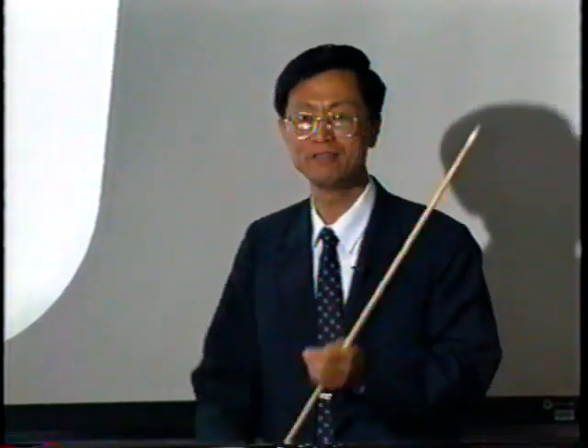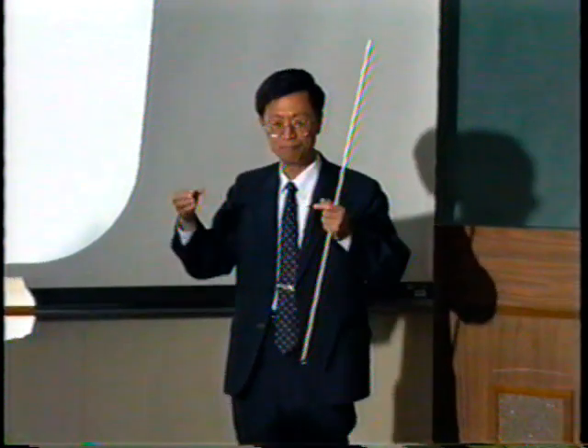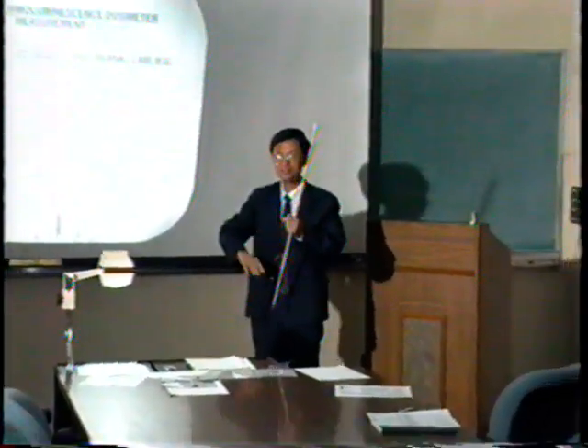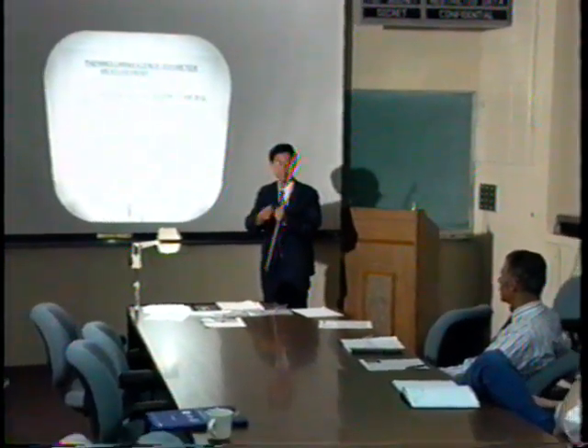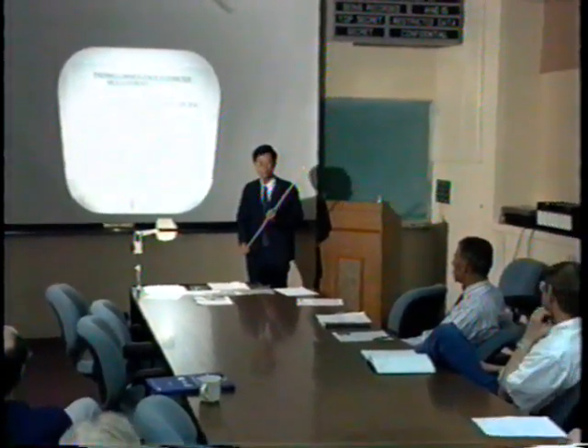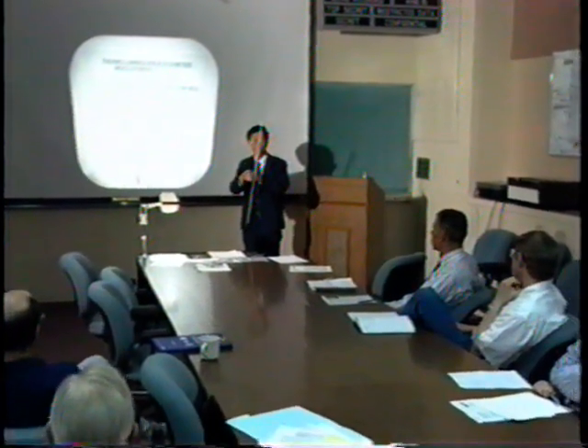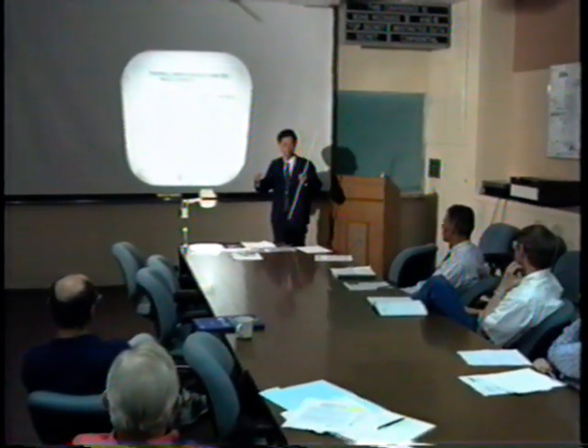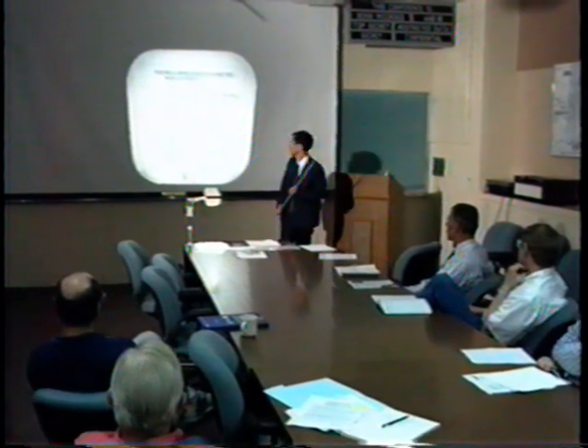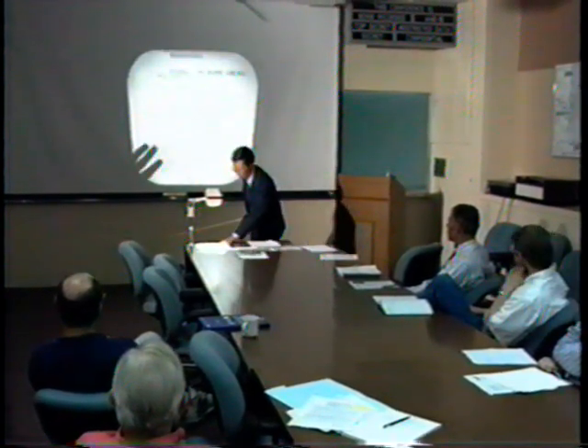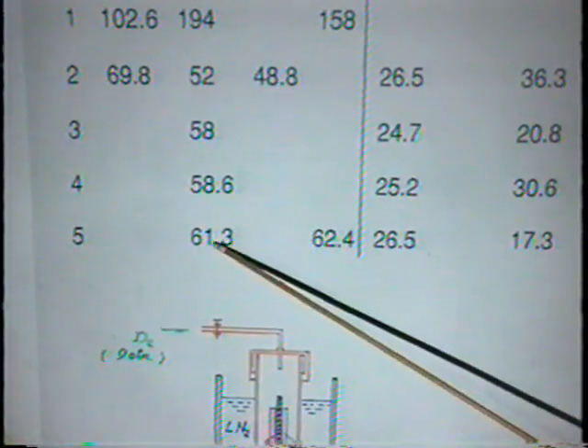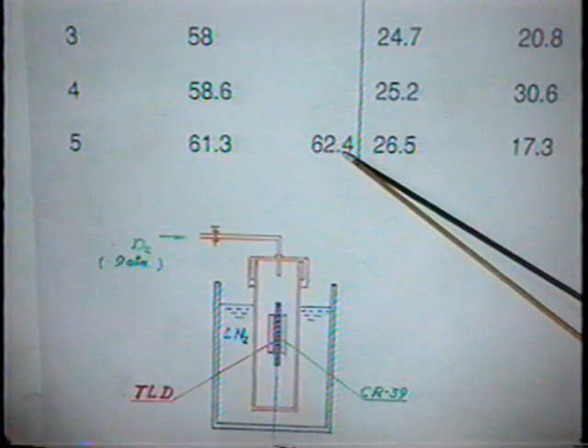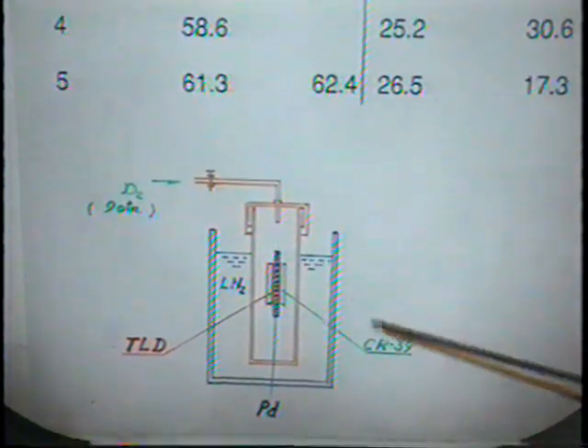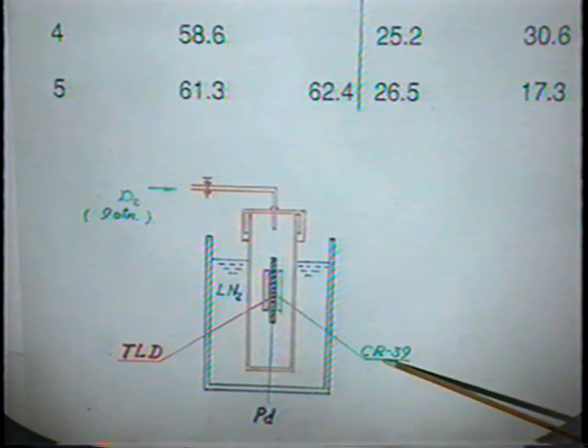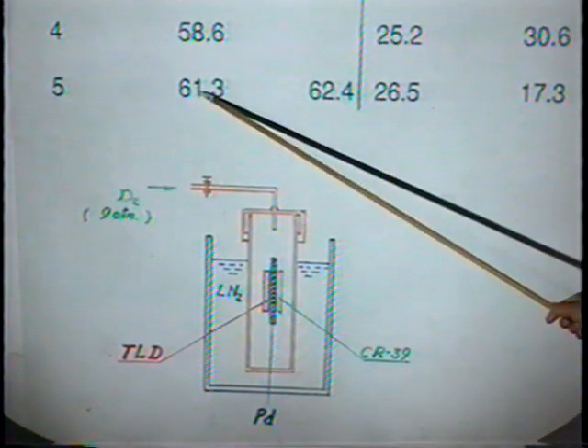Yeah. This fits with our theory because we believe the hydrogen or deuterium get into the crystal, and during this temperature cycle they will change their state and emit some electron radiation. But some of this state will help the deuterons interact with each other, then create charged particles. So if we take out this, we have the TLD signal from both hydrogen and deuterium. But for the CR39, we have signal only with the deuterium.